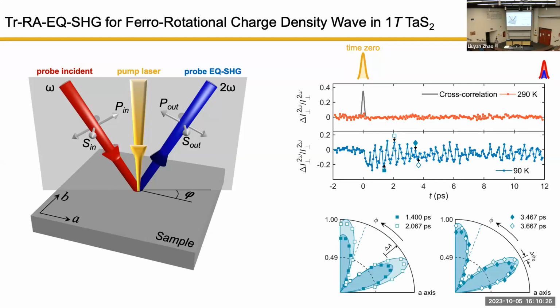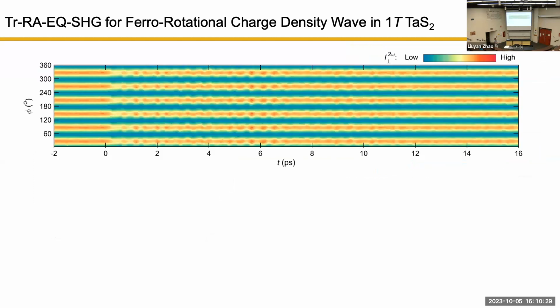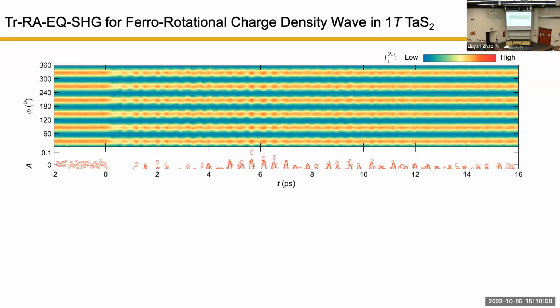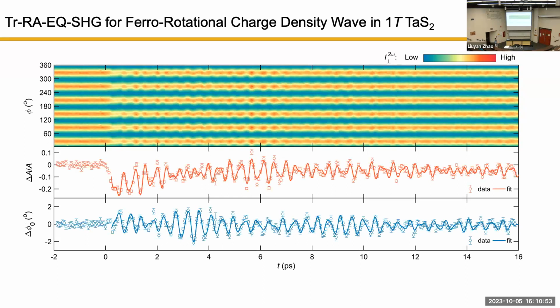In order to disentangle these two cases, we really have to do a hard measurement, that is, at every delay do a flower pattern. This is a false color map of the flower pattern at every delay. A vertical cut at a given time is one flower pattern. For every flower pattern, we get the magnitude and also the orientation of the flower pattern. So we get these two data sets here, and they are independent of each other now. The interesting thing is that the beating profiles for these two traces are actually different, which tells us that we have at least three frequencies in these two channels.